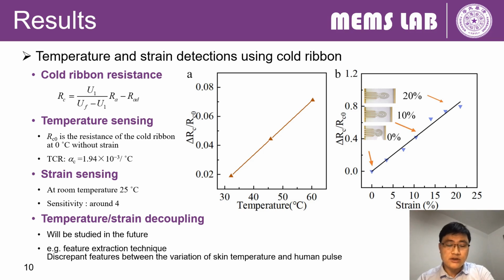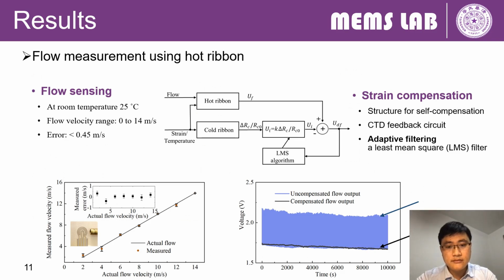Decoupling of temperature and strain sensing is an interesting topic. A feature extraction technique may work to deal with this issue. For example, decoupling of skin temperature and human pulse, which will be conducted in our future work. Here, the graph shows the response of the hot ribbon against flow velocity, which indicates that the sensor is able to detect the flow velocity from 0 to 14 meters per second with errors less than 0.45 meters per second.